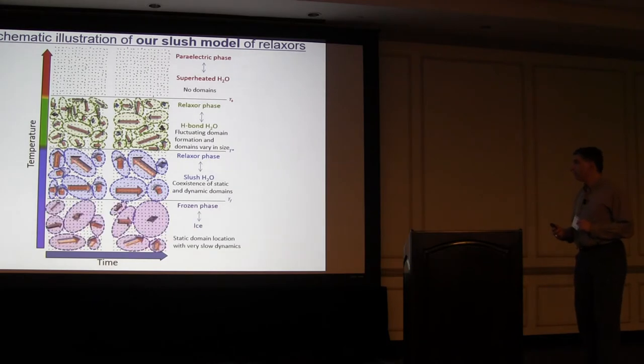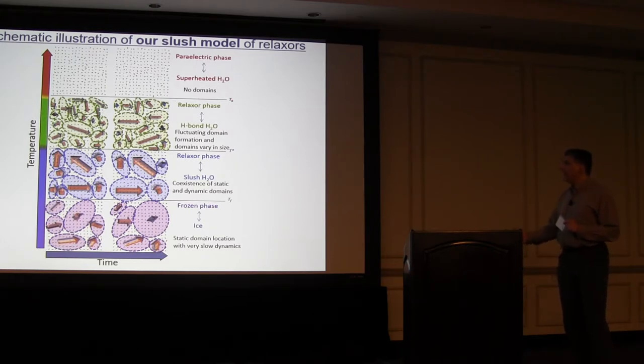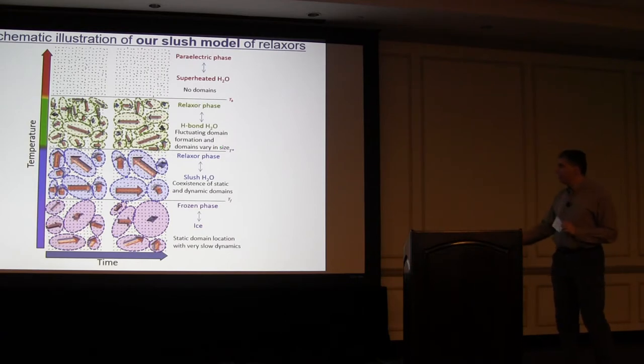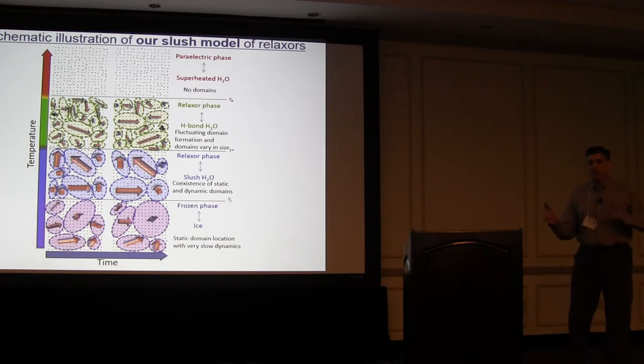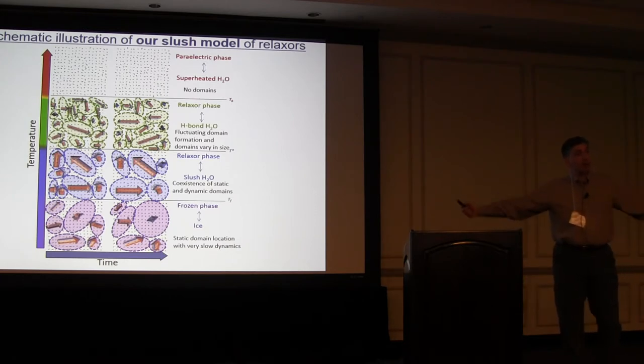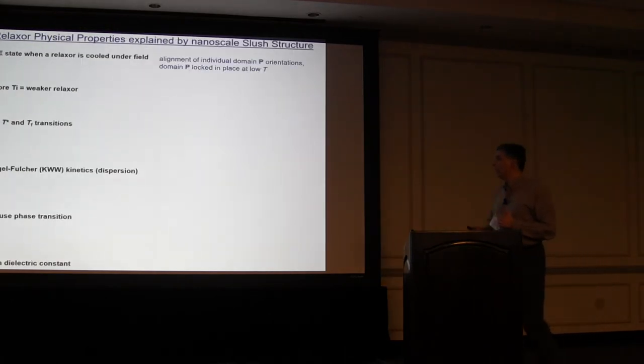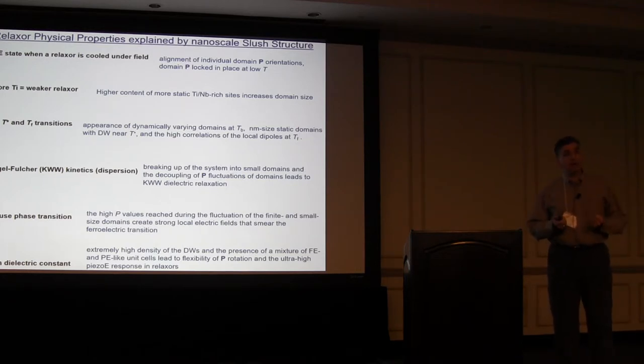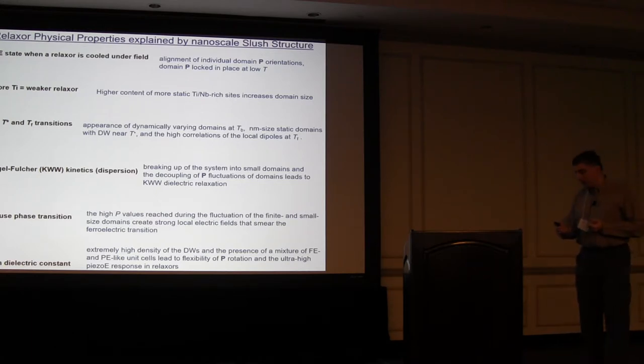Inside 6 nanometers the dipoles are somewhat more correlated and pretty correlated, but still averaging 20 degrees apart — not like conventional freezing. We have a fixed size of polar nanoregions that become more and more polar as you cool. From domain to domain you see what we call small-angle domain walls, with less than 60-degree angle deflection from one domain to the next. This is our new picture of the relaxor ferroelectric. This theory provides understanding of many different experimental observables and predictive guidance for how to make better relaxor ferroelectrics — a key driver of next-generation sonar piezoelectric devices.